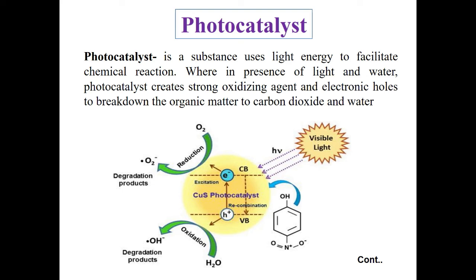This picture suggests that copper sulfide nanoparticles are used as a photocatalyst, and the gap between the valence band and conduction band is called the band gap. Because of the formation of the electron and hole pair, the band gap is changing, and because of the change in the band gap, this material can act as a good photocatalyst for the oxidation of